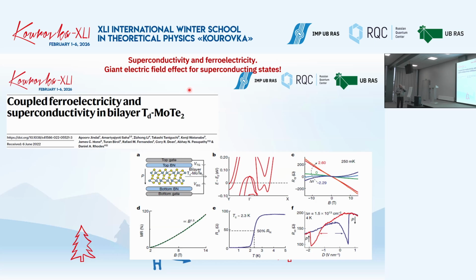And this is a recent experiment, a little bit more than 3 years old, in so-called van der Waals systems, bilayers. It's molybdenum telluride bilayers, and the picture you can see here in the center. And experimentalists are very smart, so they can arrange the application of voltages, of potentials to the structure in such a way that they can use one of the electrodes which is in the center of the structure, just between the layers, and two others up and down.